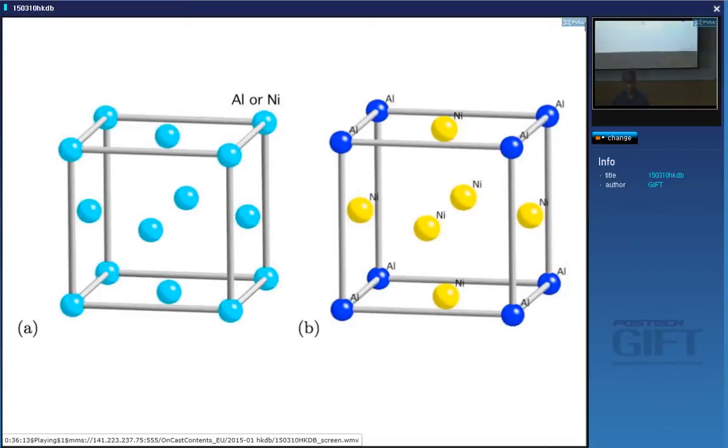Supposing you have grains, what happens to the grains at high temperatures? The grain size increases, right? The structure coarsens. And that coarsening process is driven only by minimization of the total interfacial area, right? Now, if you make a strong material for high temperatures, then reducing the interface energy reduces the coarsening rate. And this system is perfect for that.